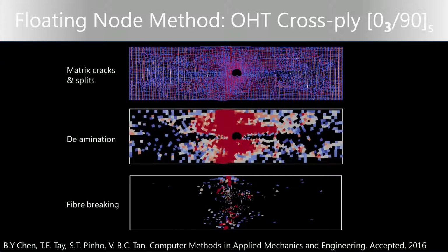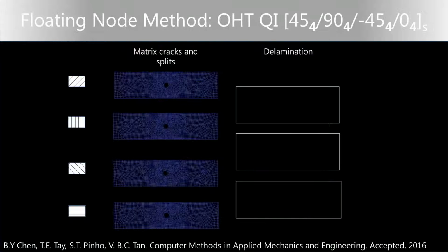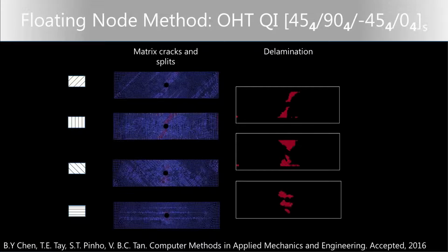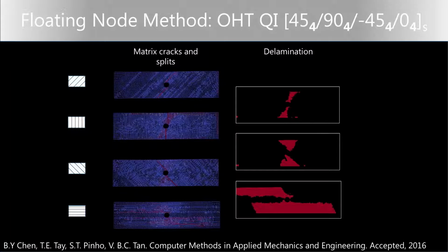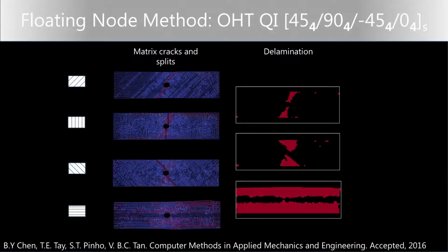Now, if this is the simulation you've seen with the greatest number of cracks, it will not remain so for very long, because in this specimen now, we have fibers not only at 0 and 90-degree directions, but also at plus and minus 45s. So now we have 3 different interfaces between the plies in the different directions. And the number of cracks that we simulate in this case is actually really, really large. You can see many cracks happening in all of these plies and the delamination between the plies growing progressively.